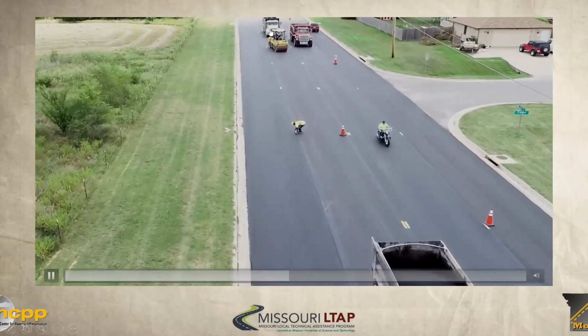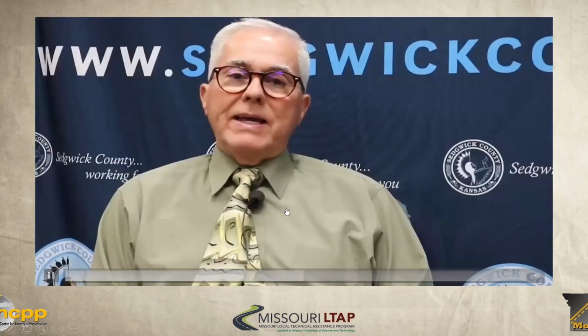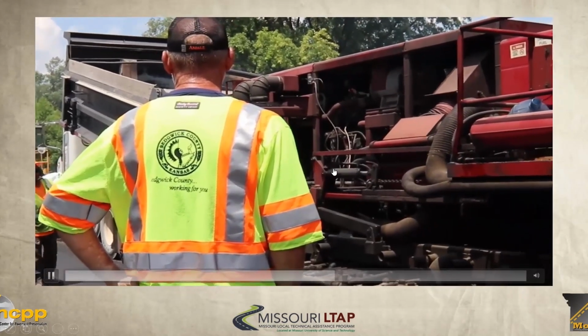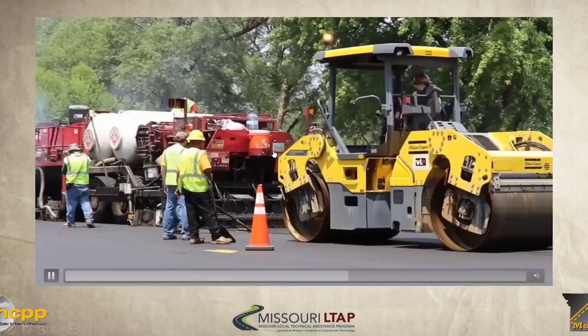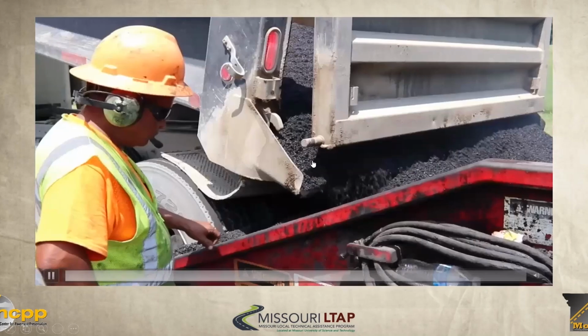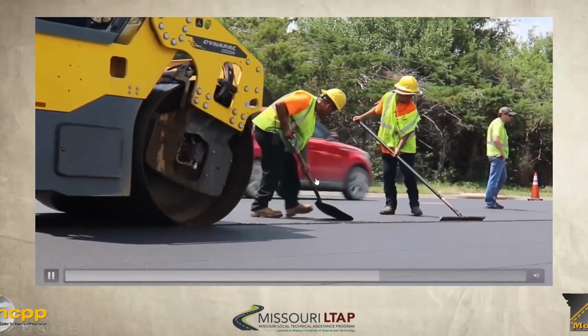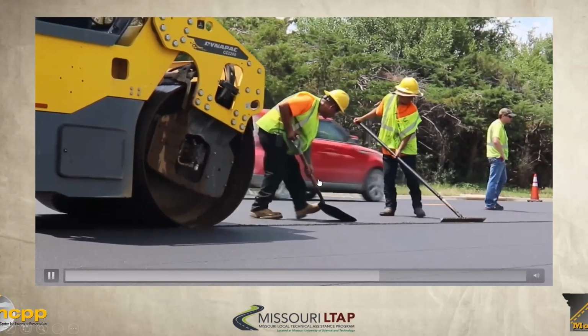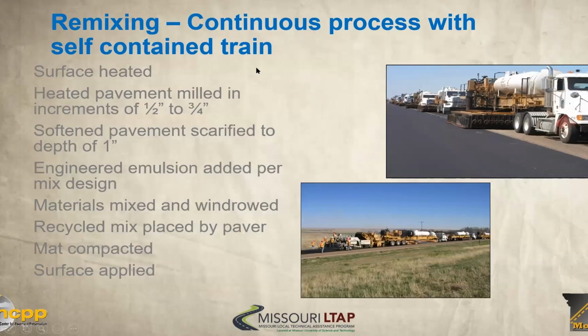Thank you, Larry. What you can see here is that they're basically using a hot in place recycling process that's going to remove the distressed, old oxidized pavement, and then hot in place recycle that. This specific strategy is repaving. It's a continuous process with the self-contained train. You're heating the surface, you've got heated pavement milled, and then we're able to inject emulsion per the mix design, mix and use a windrow, and place the recycled material by the paver and then compact that.